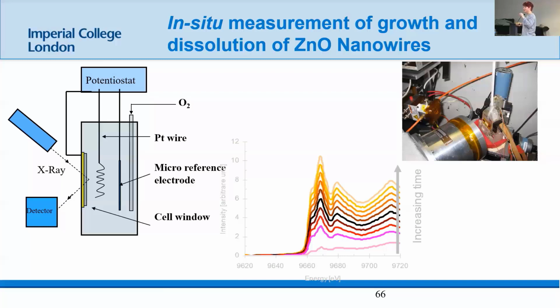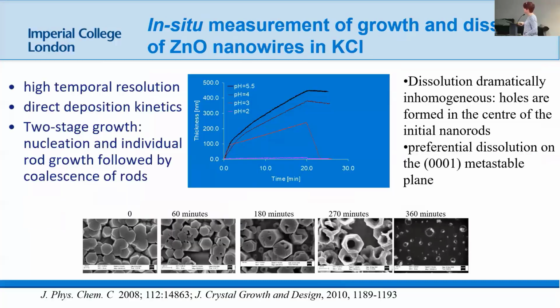But that's really important, because what that means is I don't need to take full spectra. I can sit at one place and just count, and know that I've got much better time resolution and I'm only forming zinc oxide. So this is what you then get if you do that. You get really accurate species-specific deposition rate versus time as you play with whatever parameter you want. And this approach, we've applied to measuring dissolution as well. When you do your experiments like this, if you design it properly, you can be super sensitive to a monolayer of dissolution from your surface into your sample.